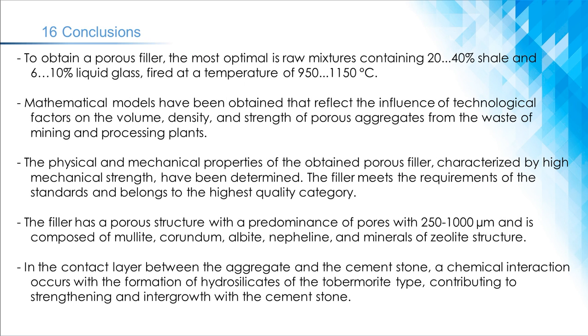Conclusions. To obtain a porous filler, the most optimal are raw mixtures containing 20–40% shale and 6–10% liquid glass, fired at a temperature of 950–1150 degrees C. Mathematical models have been obtained that reflect the influence of technological factors on the volume, density, and strength of porous aggregates from the waste of mining and processing plants. The physical and mechanical properties of the obtained porous filler, characterized by high mechanical strength, have been determined. The filler meets the requirements of the standards and belongs to the highest quality category.